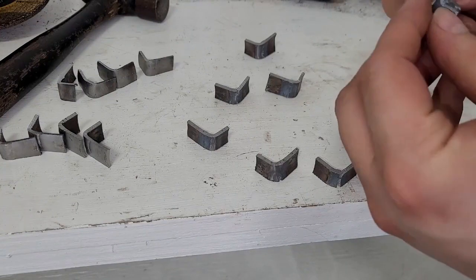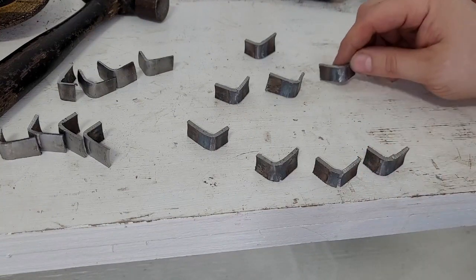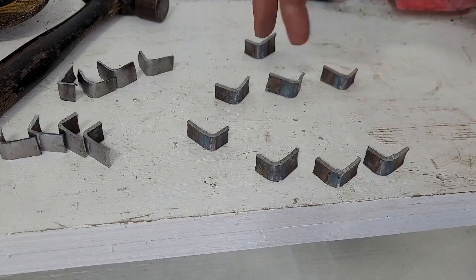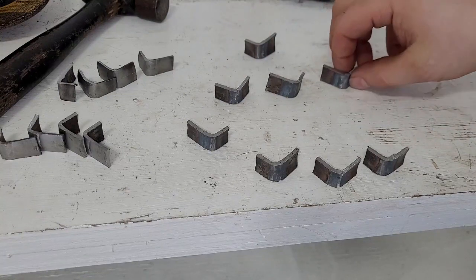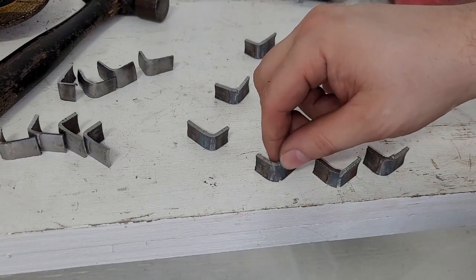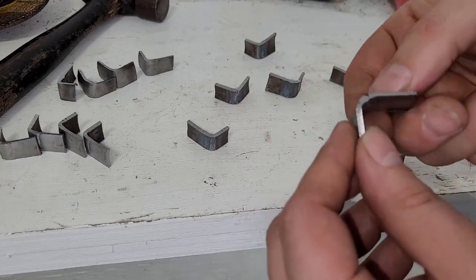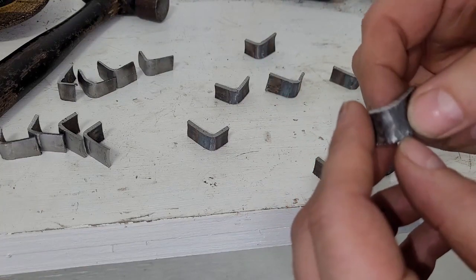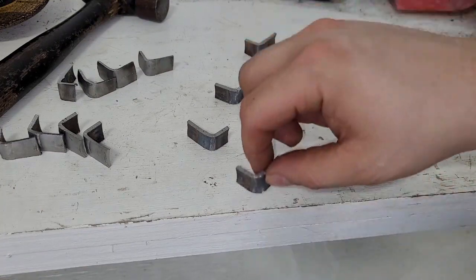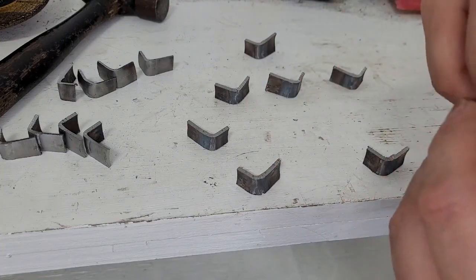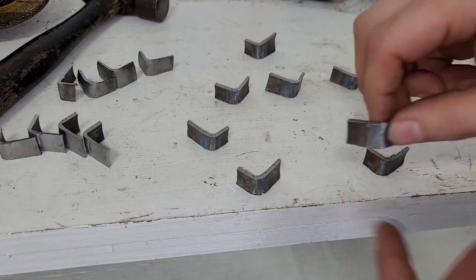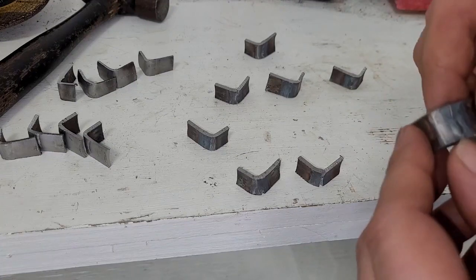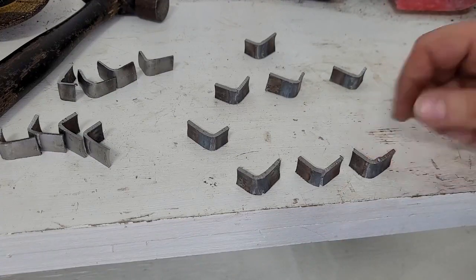And this one, let's see, we said, okay, this one cracked in the heat affected zone. So 2 of these cracked where we didn't have material. This actually cracked in the heat affected zone. And then of these 3 that cracked, that cracked where we didn't have material. This one didn't have material and totally just brittle failured. And this one cracked where we didn't have weld.